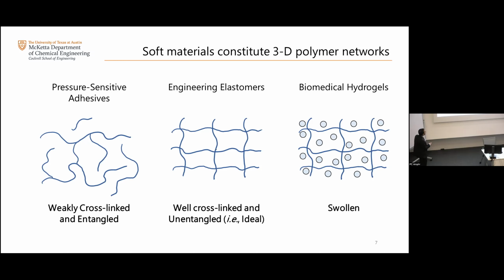So if they're very weakly cross-linked and highly entangled, they're very viscoelastic, they're more adhesive in nature. If they're well cross-linked, unentangled or entangled, you can idealize this schematic as you want, but these are more elastomeric in nature. And then if you put solvent, you are in a situation where you are a gel, organogel, hydrogel, depending on whether the solvent is water or not. So what I'm going to be focusing upon are systems that are like this. They're well cross-linked. They have defects for sure. It's an ideal picture again. And I want to discuss what is the molecular picture behind them that leads to fracture.